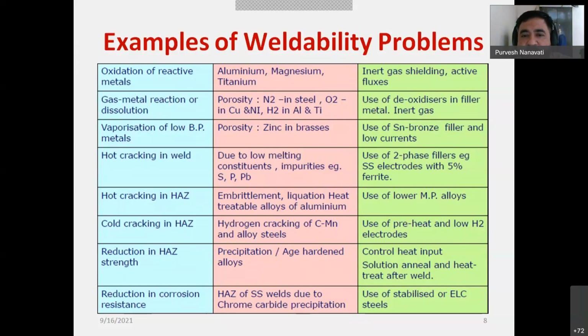Then there will be vaporization of low boiling metals, right? So porosity in the zinc brasses may happen because zinc evaporates because of its low melting temperature, like 440, 450 something. Zinc evaporates very fast, so it leaves behind the matrix of copper. You have a porosity problem, so you have to use tin bronze filler at low currents.